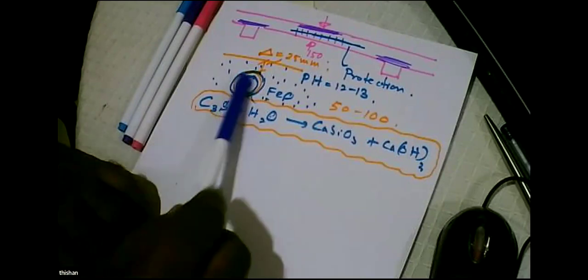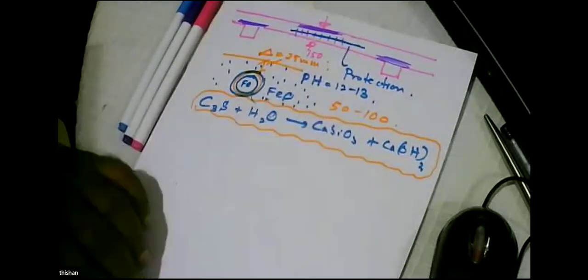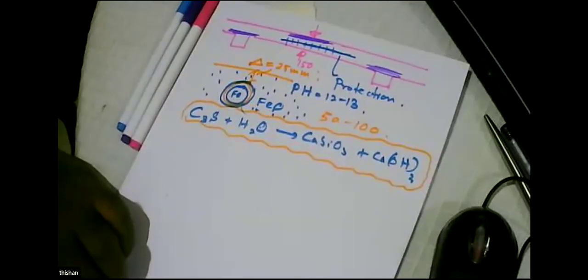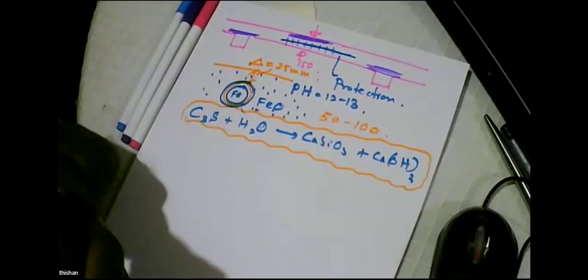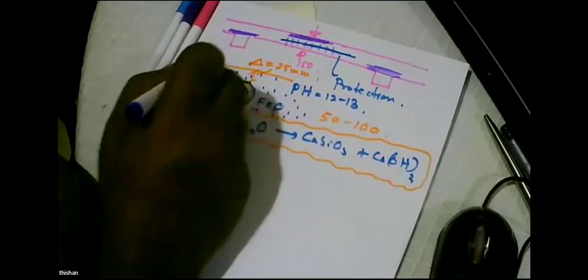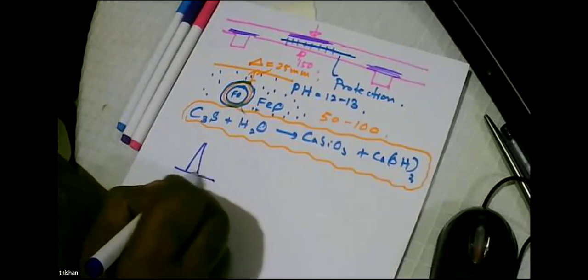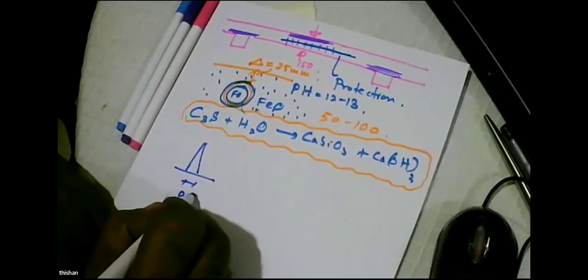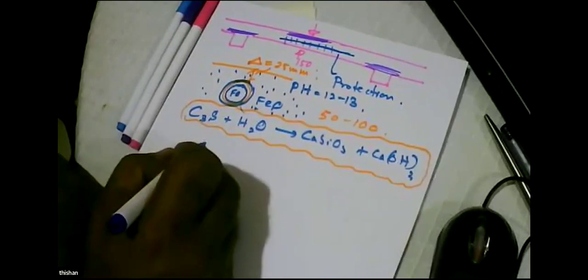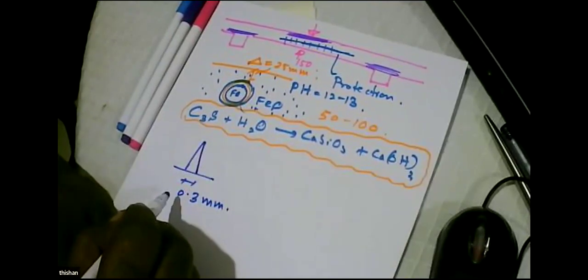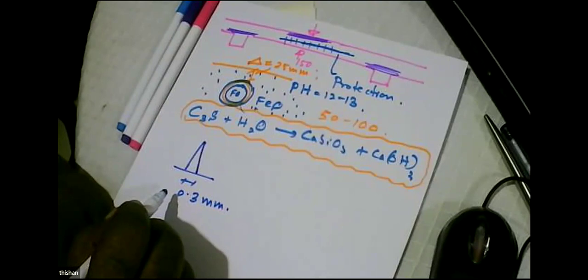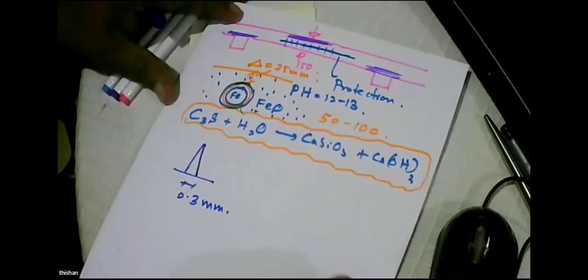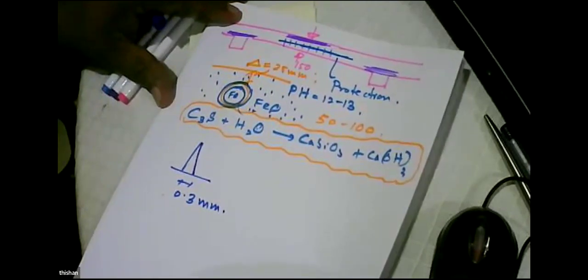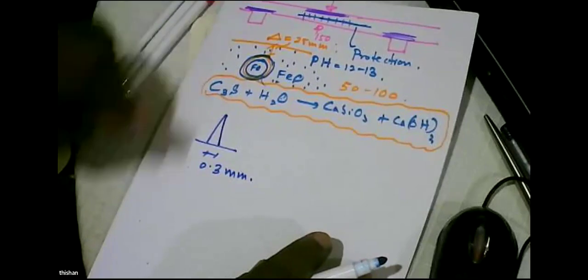So if we cure concrete, then the whole purpose of this crack control, cracked concrete, is to protect steel. And this, when we say cracked, we are talking about a surface crack width of 0.3 millimeters. But it rapidly diminishes in width, and by the time it reaches the reinforcement, it's negligible. So that's the kind of crack that is allowed. And so generally, we can't see any of these cracks because they are so fine, we can't see them.